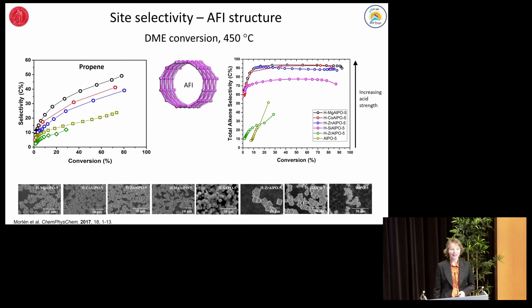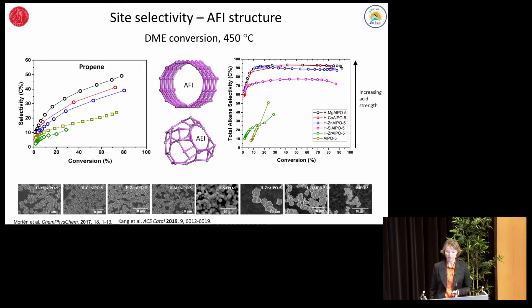As shown in the left-hand panel, the selectivity to propene was also higher in the materials with higher acid strength. Interestingly, the Davis group recently presented a similar series of catalysts with a cavity eight-ring window type AEI structure. In that structure, propene selectivity decreased slightly with increasing acid strength, and the higher acid strength favoured hydrogen transfer reactions. The opposite trends observed for the two series of materials clearly demonstrate the importance of zeolite topology for catalyst performance.